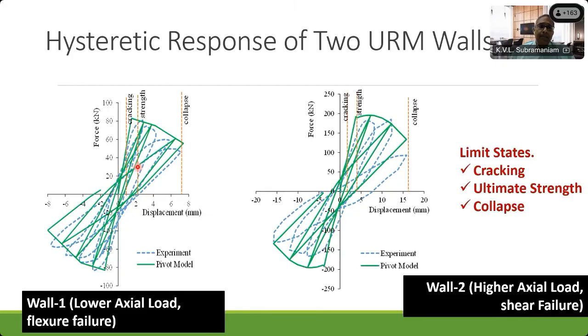Now, the next thing is we have the simulated responses that we are able to do for different walls. Here, wall 1, suppose I take with the lower axial load. When you take a wall which has a low axial load, it will fail in flexure. It fails by a pivot model, so we calibrated a pivot model to this response. Take another wall which has a higher level of compression on it, so higher axial load. This fails in shear. And again, this is calibrated with a pivot type of model that you see around here.